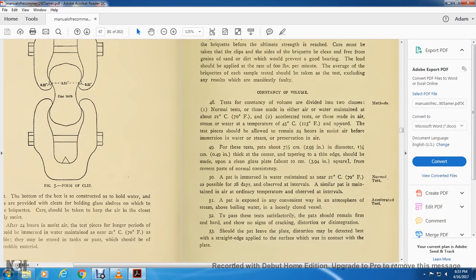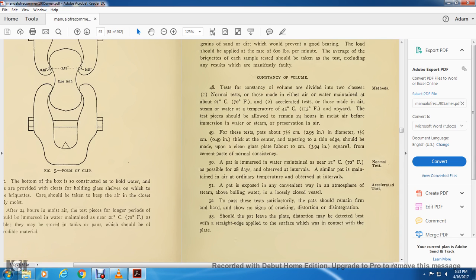For the test pats, 7.5 centimeters in diameter and 1 1/4 centimeters thick at the center, tapering to a thin edge, should be made upon a clean glass plate about 10 centimeters square from cement paste of normal consistency. A pat is immersed in water kept as nearly as possible at 70 degrees Fahrenheit for 28 days, and observed at intervals. A similar pat is maintained in air at ordinary temperature and observed at intervals. A pat is exposed in any convenient way in an atmosphere of steam above the boiling point in a loosely closed vessel. To be satisfactory, the pat should remain hard and show no signs of cracking, distortion, or disintegration.